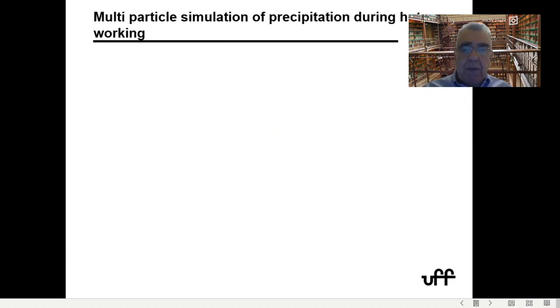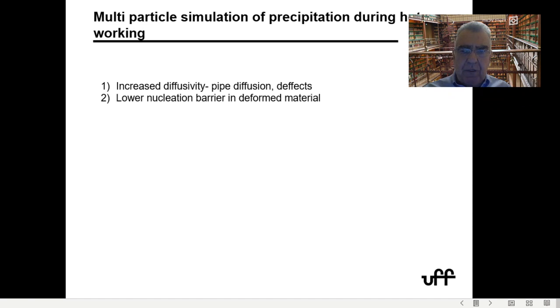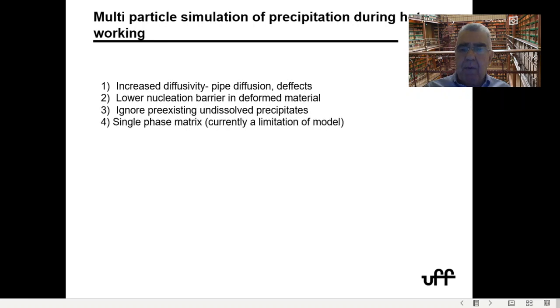Now, when you do multi-particle simulation, you have to take into account that there's increased diffusivity, maybe because of pipe diffusion. The nucleation barrier decreases because you have deformed material that has maybe higher energy. And the models cannot take into consideration the undissolved precipitates. So you have to, in principle, ignore that there is a little particle there that is going to act as a nucleus for what's going to happen. And then we don't have a model yet that can do, for instance, interphase precipitate. We can only do a single matrix. But this is already a big challenge if you're looking at the carbonitrides in austenite.